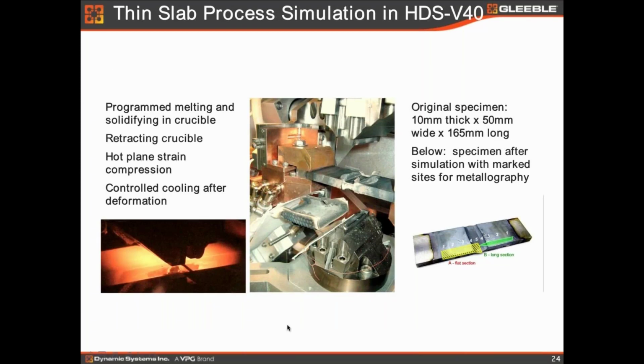And this photo we show deliberately to show the kind of liquid. And we deformed while the specimen is still in the semi-solid region. So you can see some of the mushy zone out of this. But as I'll show you, you can deform at any temperature you want, any strain rate or strain you want. You don't really want to make it mushy, right? But I propose to do this because you want to show the HDS can do whatever you want to simulate,